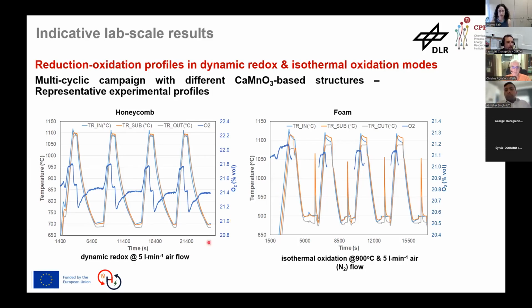In the dynamic redox process, oxidation begins immediately after the temperature starts to decrease after the peak. In contrast, during the isothermal oxidation, the system is cooled under nitrogen flow to the target temperature, at which airflow is introduced to trigger oxidation.